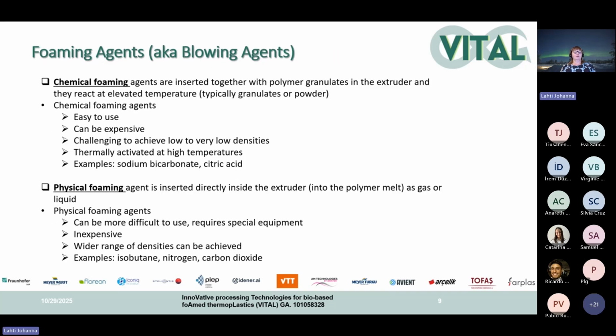Then in foaming processes, we use typically so-called foaming agents or blowing agents. And for that, we have two different types of agents that can be used. First, we have chemical foaming agents, and they are inserted together with the polymer granulates in the extruder. And in the extruder, they react at these elevated temperatures, and then we create the foam. And typically these chemical foaming agents are also granulates, or they can be powder format.